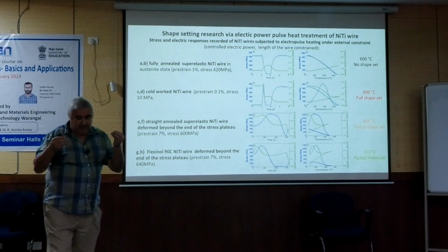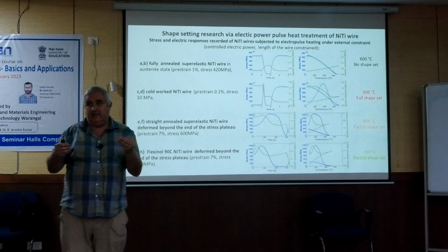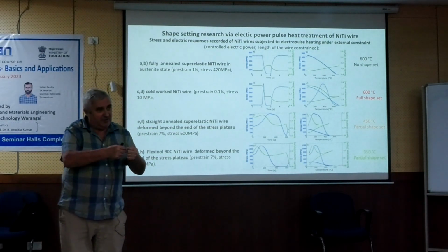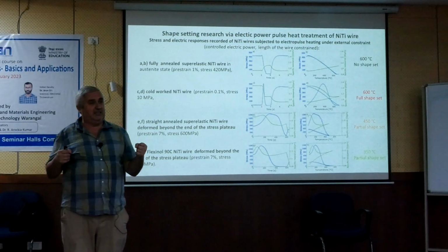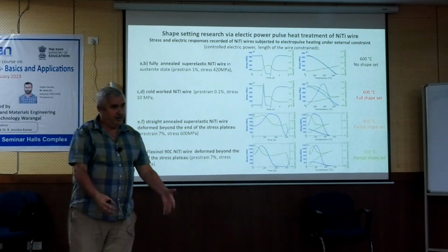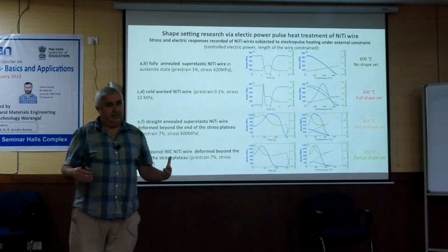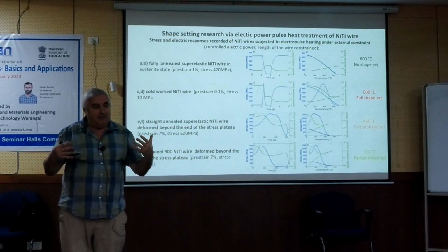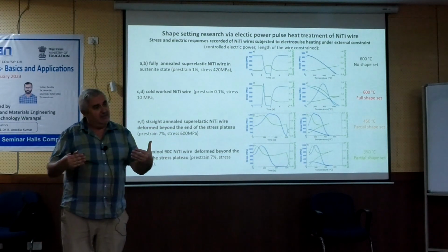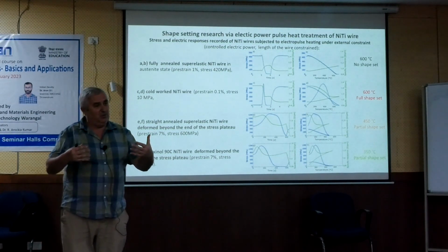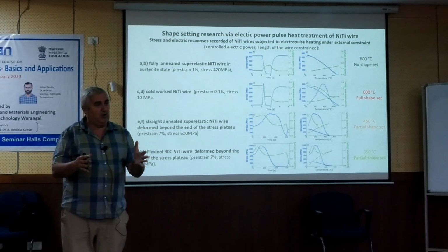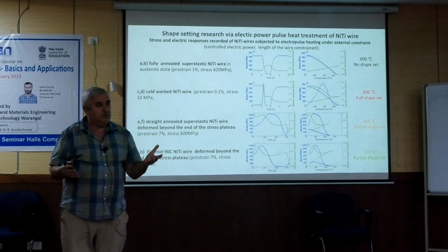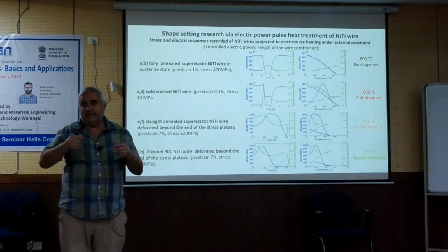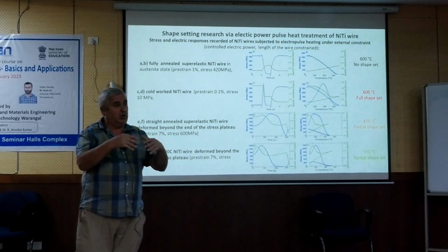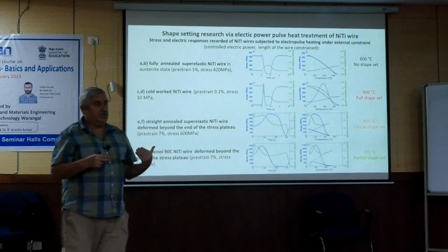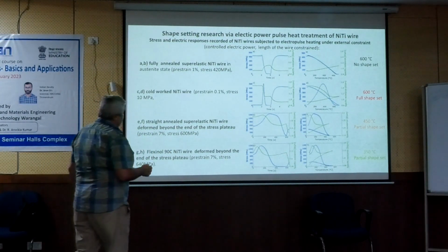So if I have the super elastic wire and I want to shape set it, before shape setting it, it's necessary to stretch it to the martensitic, or you can decrease the temperature. At low temperature it's easier to do. But the annealing has to be done in the martensite state. The martensite state is the one which gives you the possibility to give it the new shape. And this is different from steel. In steel you don't care. You just bend it and heat it to high temperature, plasticity will occur and will shape set the spring. But in case of nitinol, you have to be in the martensite.